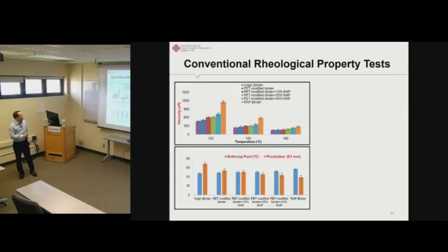So from this plot, we can see the trend is very clear. If we add the PET additive, we can see it slightly increases the viscosity of the binder. And if we further add the wrap binder, as expected, the viscosity will be further increased. And for the softening point and penetration, we got a similar trend. For the softening point, if we add a PET additive, the softening point is slightly increased, and for the penetration, if we use the PET additive, the penetration slightly decreased.